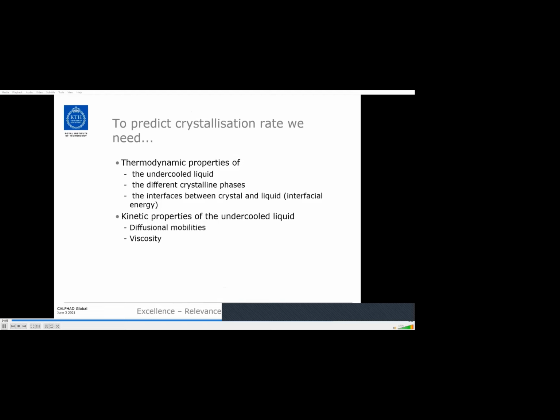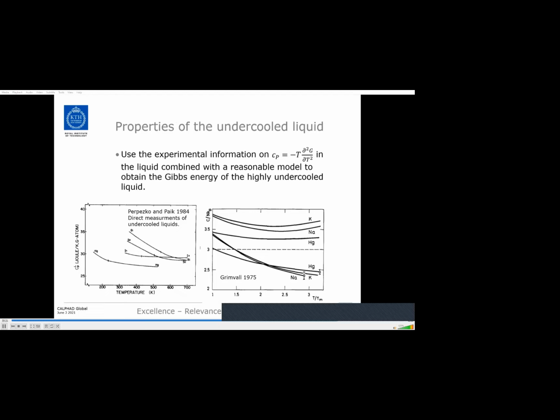So to predict the crystallization rate, we need thermodynamic properties of the undercooled liquid, the different crystalline phases, and the interfaces between the crystal and liquid, and that is the interfacial energies. We also need the kinetic properties of the undercooled liquid, so the diffusion mobilities and the viscosity. For the properties of the undercooled liquid, we can use experimental information on the heat capacity, which is proportional to the second order derivative with respect to temperature of the Gibbs energy. And we must combine that with a reasonable model to obtain the Gibbs energy of a highly undercooled liquid. And we see from the experimental information that the heat capacity increases when we cool the liquid without crystallization.